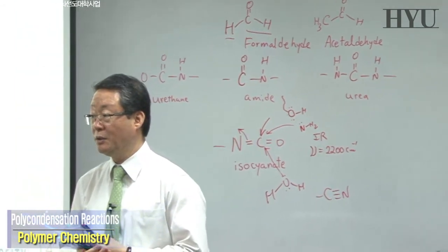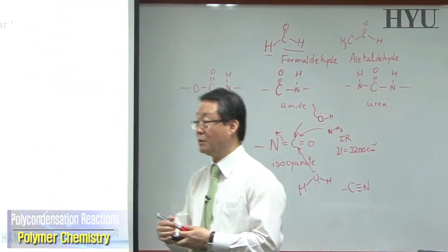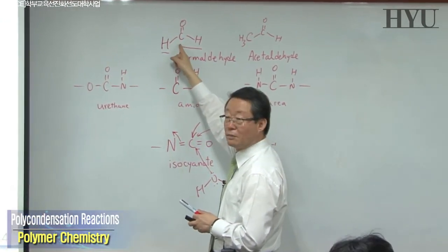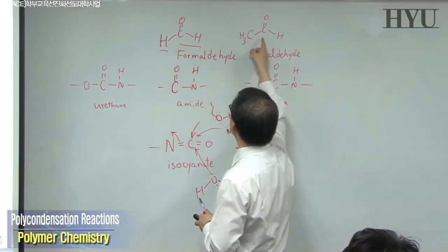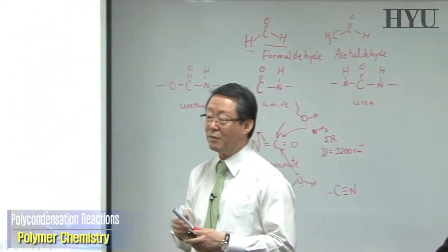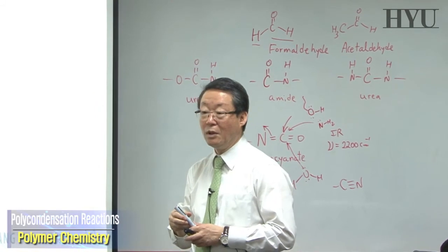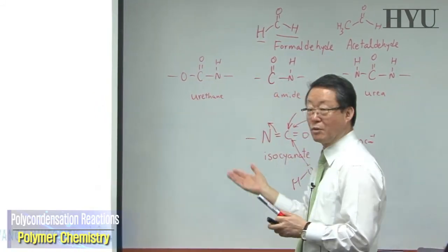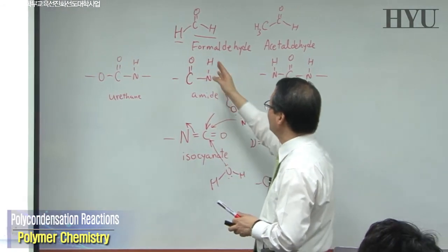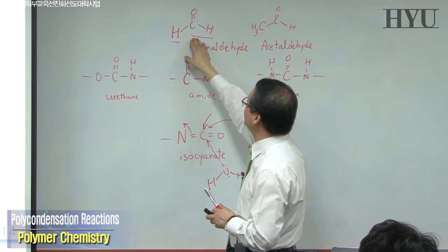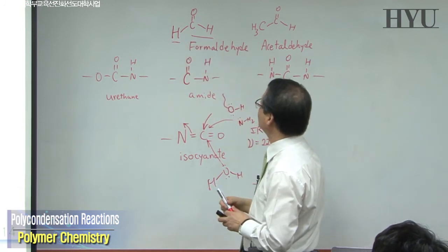This CHO is very characteristically characterized because you have a carbonyl group. This carbonyl group can be found around 1700 reciprocal centimeters, but depending upon whether it is a carboxylic acid or an aldehyde, we have a different shift. Anyway, you can take a look at 1700 in the case of aldehydes.